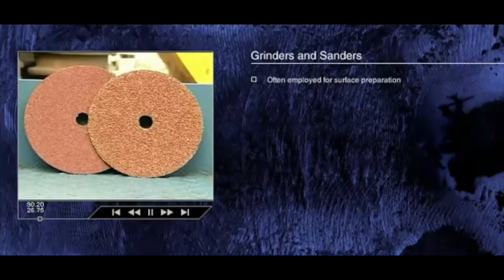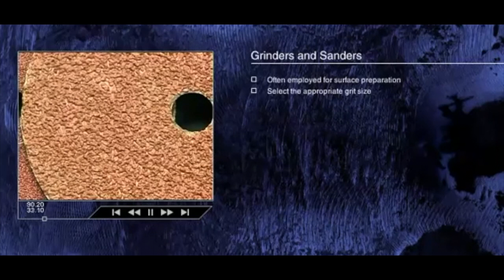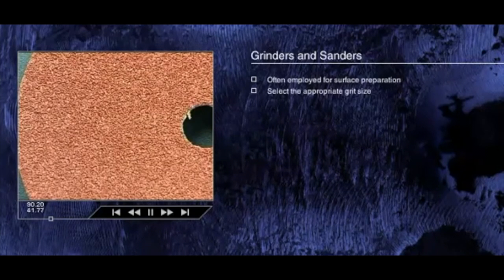The abrasive grit size used with this type of cleaning equipment must be selected properly. Too coarse an abrasive will create a deep anchor that may be unsuitable for good paint performance. An abrasive that is too fine may cause early clogging of the grinding wheel or sanding disc, thus making the process inefficient.